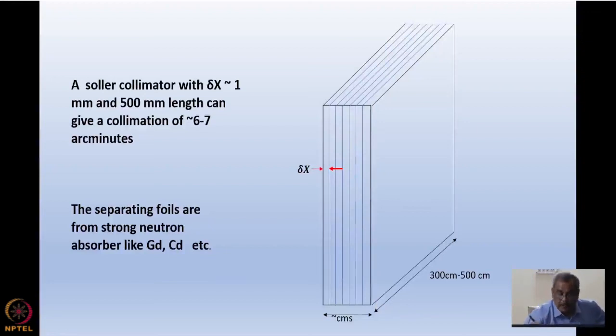And the collimation is given by delta x, which I have defined here, which is the distance between two of such absorbing materials. These absorbing materials run all throughout the length of the collimator. And actually the beam divergence is dictated by the delta x, which I showed here in this diagram. The separating foils are made from gadolinium or cadmium. And we have to take lots of pain to keep them straight, stretched, so that the beam path does not get closed in the length. So typically 300 to 500 centimeter length. And this is called a Soller collimator.